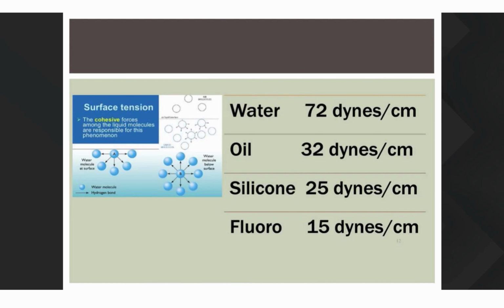So if you're foaming a hydroalcoholic solution, like perhaps many people are trying to do these days in making sanitizer, the fact that the ethanol in water is very low surface tension, you have to use a specific silicone to get low enough in surface tension to make the foam. This is an example of fitting the performance requirements to the formulation. So you can take alcohol and water and do different things with them based upon these small additions.